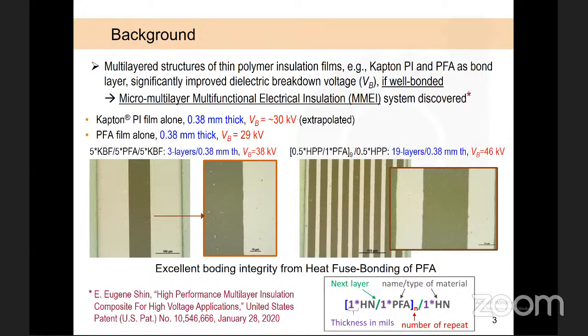As an example, for the same overall thickness, dielectric breakdown voltage VB of a 19-layer structure made of very thin layers of the Kapton and PFA was much higher than that of a 3-layer structure made of a bit thicker layers, which was yet still higher than that of the single-layer materials. Optical micrographs here confirm that heat fuse bonding with the PFA semicrystalline polymer provided excellent bonding integrity. This multi-layer structure was named as MMEI and fully patented in early 2020. The nomenclature illustrated below is the typical MMEI layup configuration convention used throughout this paper.